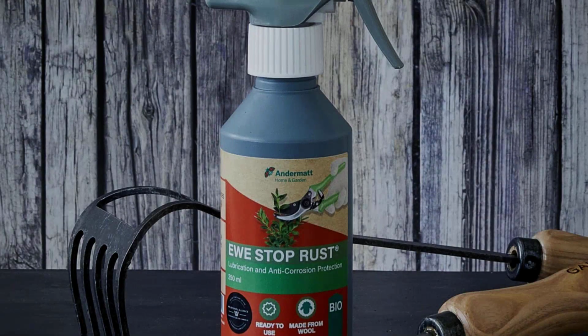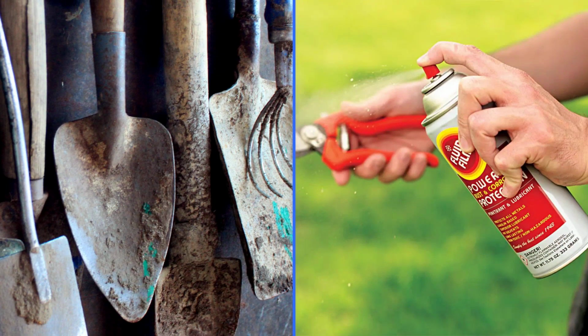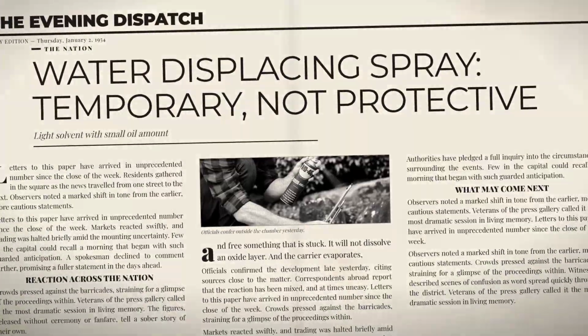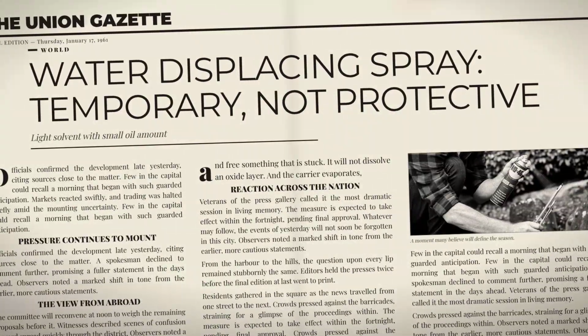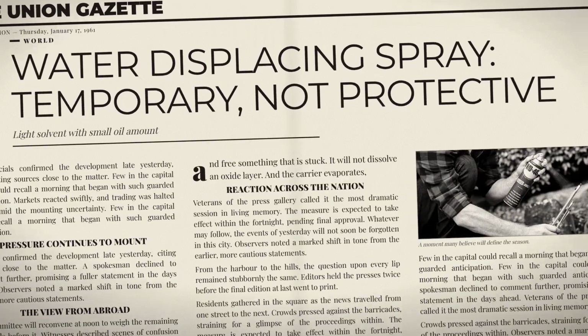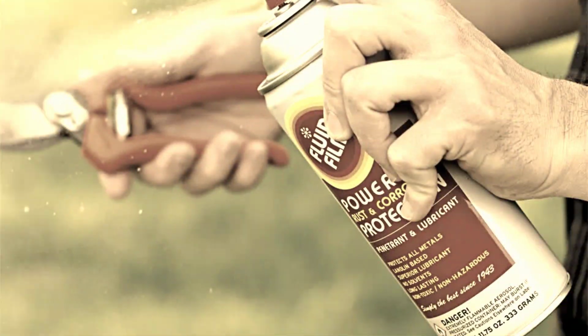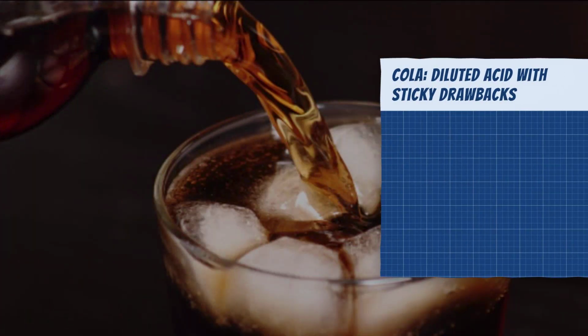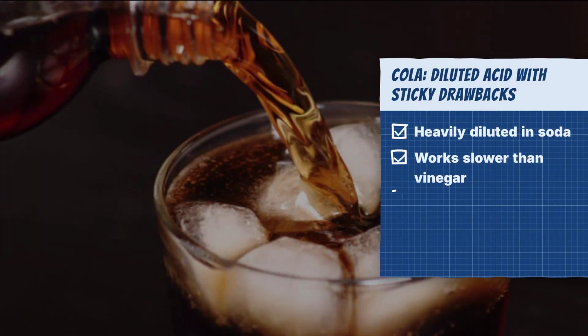Water-displacing spray is a rust remover or a long-term protectant. It is neither. The product is largely a light solvent with a small amount of oil in it, and it works exactly as designed, which is to drive water out of a joint and free something that is stuck. It will not dissolve an oxide layer. And the carrier evaporates, leaving a film so thin that in a damp shed it is effectively gone within a few weeks. Using it as your rust protection is why the tool you sprayed in April is orange again in June.